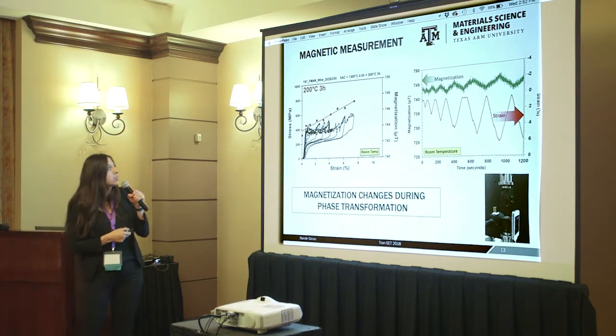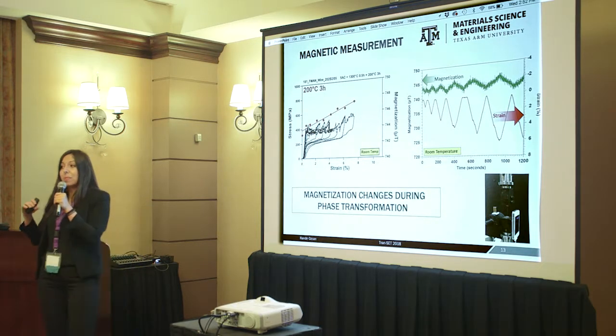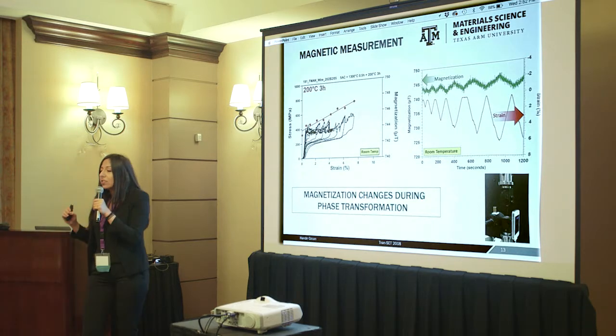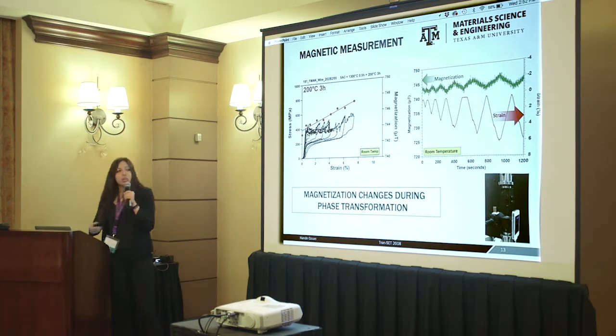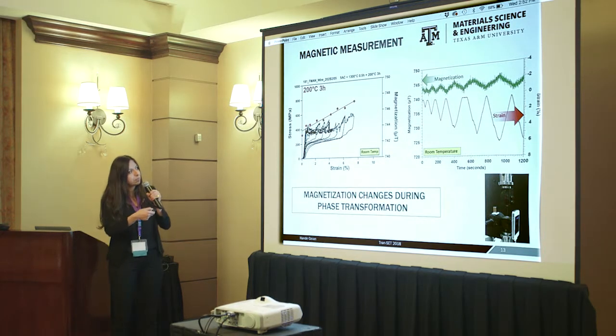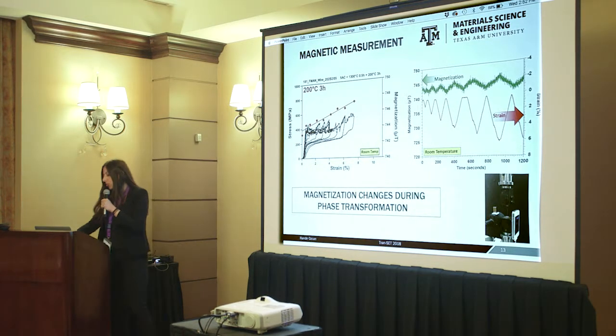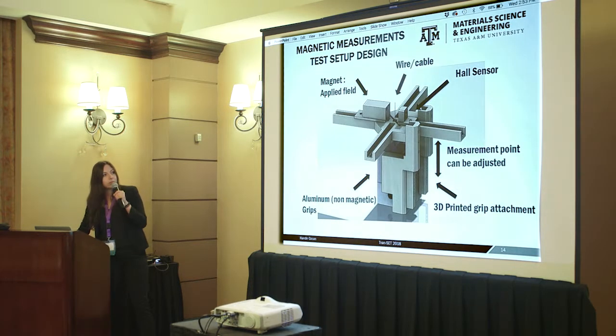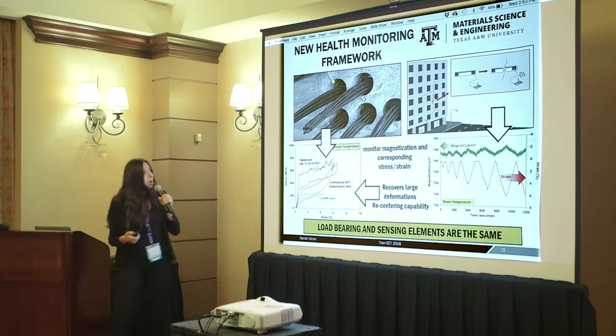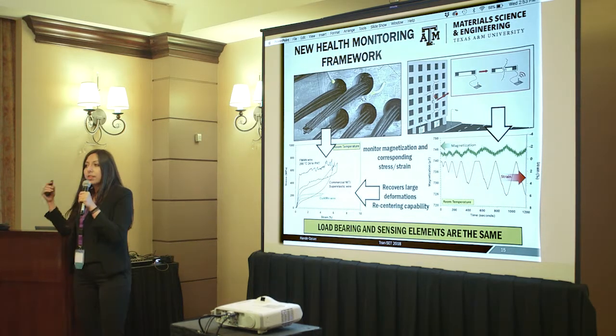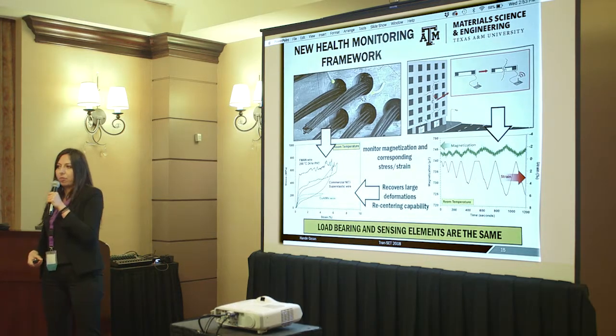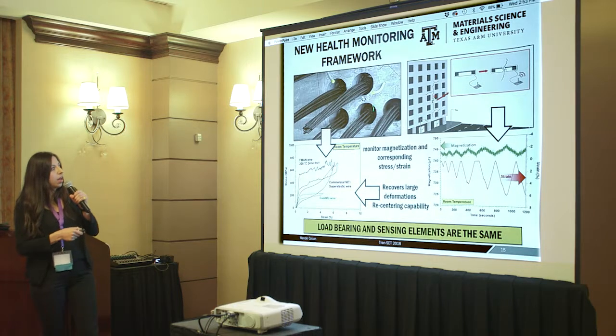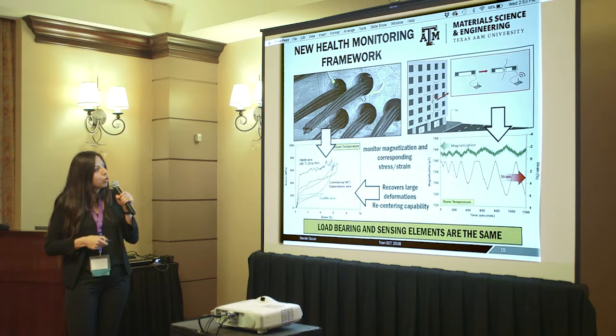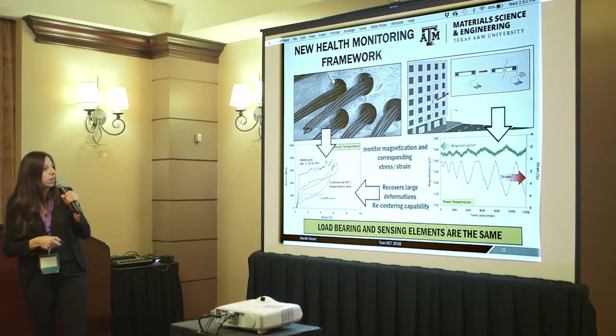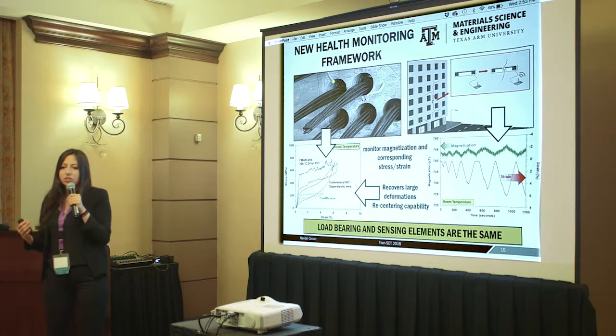We also realized that, because this is an iron-based shape memory alloy, it also changes its magnetization during transformation. This property is extremely important for us because, as you can see here, as the stress-strain changes, our magnetization changes, and we can detect this magnetization change using a sensor. I'm skipping this because we don't have so much time. So now we know that with iron-based shape memory alloys we can recover large deformation, so it has recentering capabilities, and they can also show a magnetization change during phase transformation.